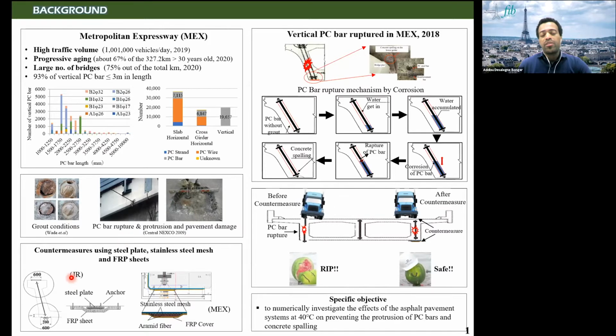In the past, several countermeasures were utilized using steel plates, stainless steel mesh, and FRP sheet. But these techniques take a longer construction time, which is not recommended for Metropolitan Expressway as the traffic volume is quite large. In 2018, an actual rupture of vertical PC bar was investigated by the authors in the Metropolitan Expressway. This figure shows how the PC bar ruptured by corrosion. If we don't use proper countermeasure, safety will be a problem. So in this study, we numerically investigate the effect of asphalt pavement system at 40 degrees centigrade on preventing the protrusion of PC bar and concrete spalling.